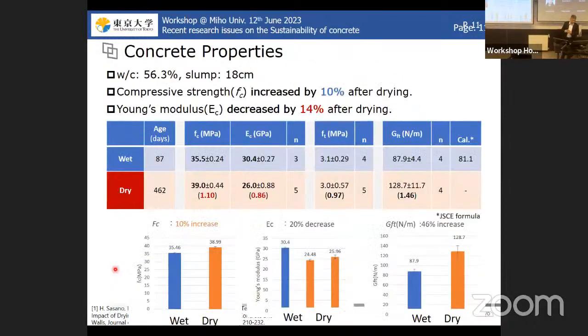I also measured the properties of the concrete. As you see, the compressive strength is a little bit increased after the drying. In the case of Young's modulus, it is reduced. And the fracture energy shows almost a 40% increase after the drying. So we have to think about the impact of these on the structural performance of the reinforced concrete shear walls.